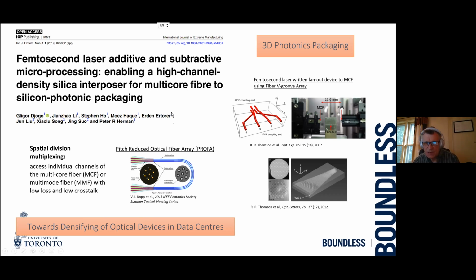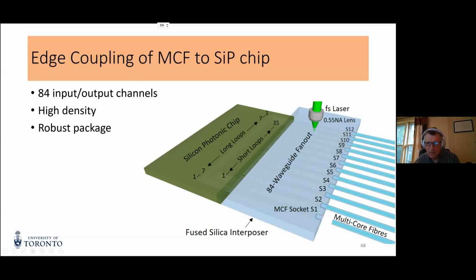And so there's this work by Thompson where laser formed waveguides are made in 3D, facilitating these fan outs. And with the fan outs, you can reconfigure the waveguides from the multi-core fiber into linear arrays to do edge coupling. So just briefly, we built an interposer and introduced these multi-core fiber sockets to improve the alignment geometry.